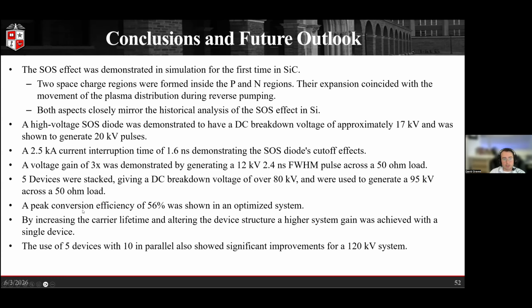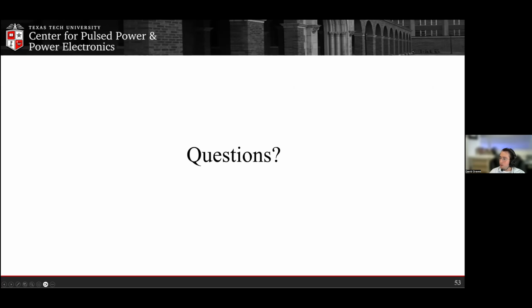Throughout some of the simulations, we did show a peak conversion efficiency of 56%, which we believe can be further increased. One of the other things demonstrated was the benefit of increasing carrier lifetime and then re-optimizing the device structure. We're able to get a higher system gain, and alongside that, much higher energy systems. So again, with the 10 strings of 5 devices in parallel, we ended up with a 120 kV system. And so with that, we're right up on time, and I will stop and take any questions.